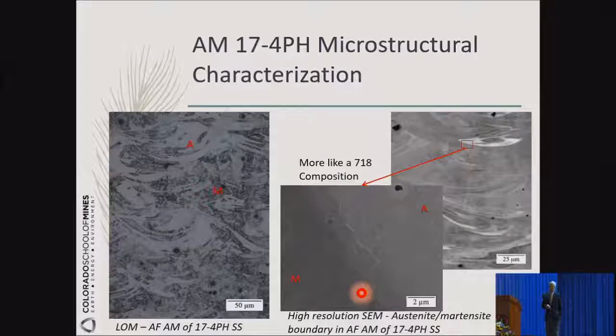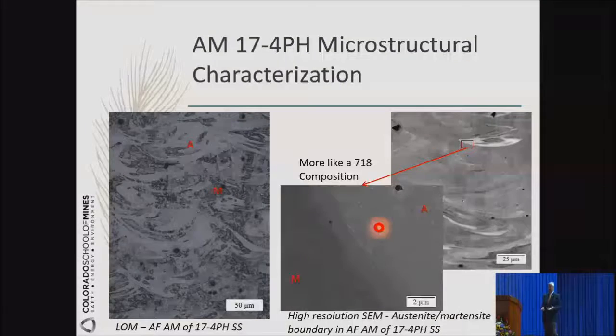So here I wanted to show you only one thing, the weldability behavior, or the difference here. You look at the left-hand side photomicrograph, that is the AM 17-4, and you see a lot of these deposits. Each one of those is actually a deposit, and there are many little swirls. Take a look on the right-hand side here. We took this little swirl and did an analysis. You look at it almost like a composite material, because on one side you have austenite, on the other side you have martensite. This side is closer to the 17-4, but this side here is more like a nickel 718. So what has happened there? Now you have literally repeating patterns of this swirl with different composition.